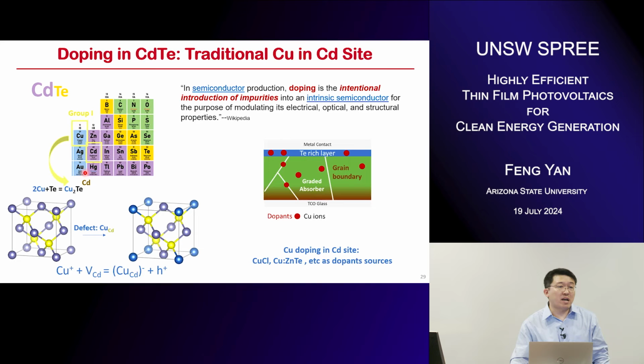Because based on the defect chemistry, we can see that copper going to the cadmium vacancy can contribute an acceptor hole inside the system. The unique thing for polycrystalline cadmium telluride is that the dopants prefer to diffuse into the grain boundary. For example, here, so then you can further diffuse from the grain boundary to the grain interior. So this is the technique. That's why a lot of work is trying to build a copper-rich layer on the back side of the film, then using thermal treatment to drive the diffusion.